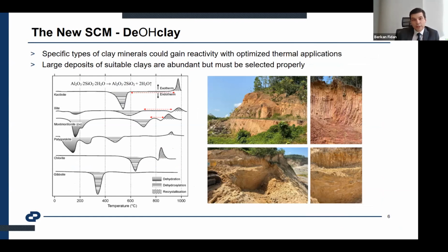According to that, specific types of clays and their thermal activation also need to be checked on the process side. When we check the specific clay minerals, that is the critical point. A hydroxyl group is removed at some temperature, but if the temperature keeps increasing, crystallization happens in all these clay minerals. And the range is critical, because on an industrial scale, to make the dehydroxylation, you need to have a range, because process control, keeping the range, and getting the best reactivity is critical to get the dehydroxylation completed but not reach the crystallization phase, because in the crystallization phase, mullite and spinel formations start to appear.